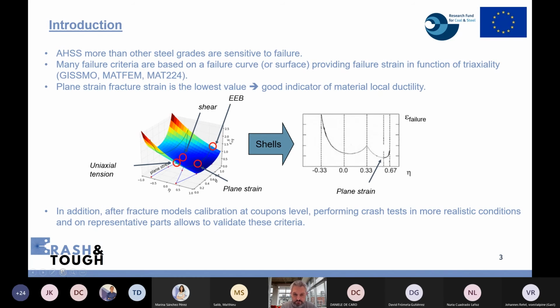If we have a look at the fracture criterion, generally it is given for a given strain path or triaxiality, depending also on another parameter, for example the load angle, so it's a criterion that depends on at least two parameters that will provide a fracture surface instead of just a fracture curve. But when we are using shell elements, it is a plane stress condition, so we can have a formulation based on a fracture strain curve. And we can see that the lowest value of ductility is reached in plane strain condition, here on the right graph, for a triaxiality of about 0.68. So that's why the plane strain condition is very relevant in order to characterize the product in terms of its ductility.